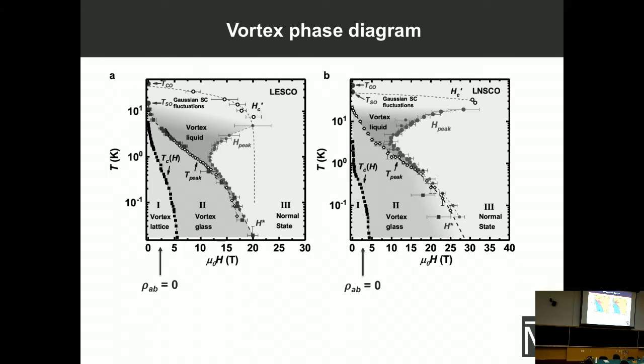This is actually the result. The temperature is on the vertical axis. Note that it is on a logarithmic scale, and we have more than 3 orders of magnitude. The black symbols are the TCs as a function of the field. This is the region where the linear resistivity is 0. Green symbols are the peaks in the magnetoresistance, and the blue symbols are the peak in the temperature dependence of the resistivity, and the phase diagrams are shown for both materials.